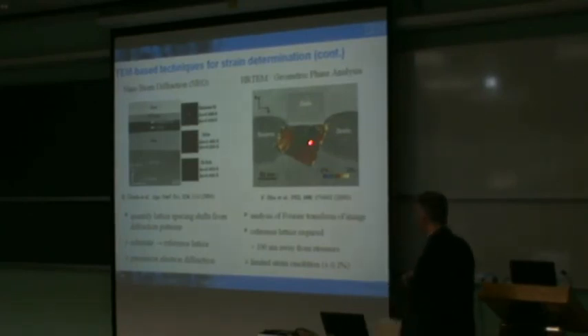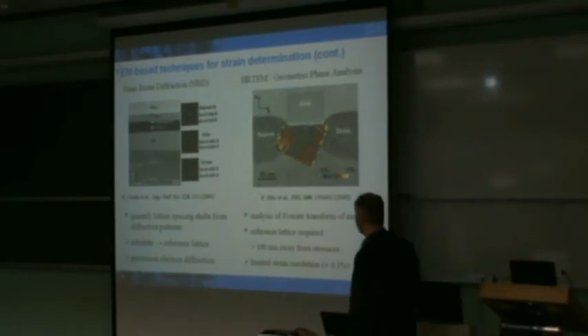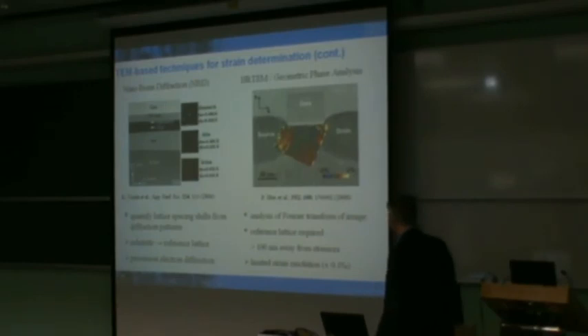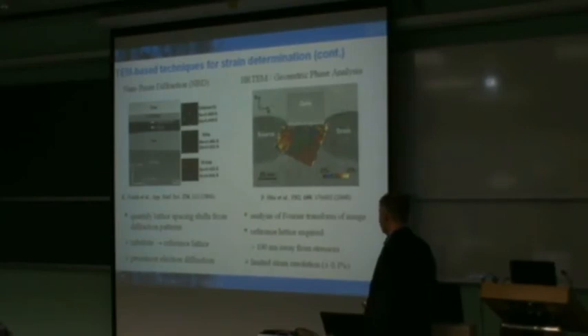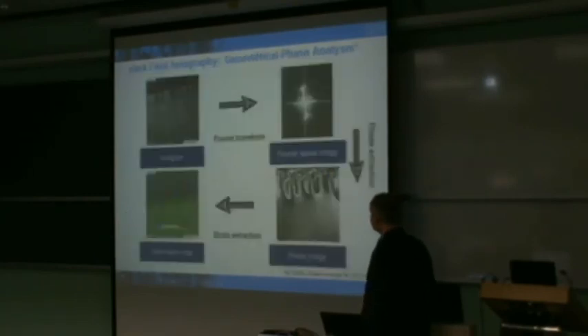Another one that's been used very often now is by incorporating the Fourier transform that we get within high-resolution electron microscopy. We can see what's going on in the channel region here, and what I'm plotting here is the in-plane strain that we can measure then. We need to get a reference value from this sort of measurement, so we have to go significantly far enough away from the channel to get the measurement. One of the key problems, of course, is that the strain resolution is something that is still needing improvement.